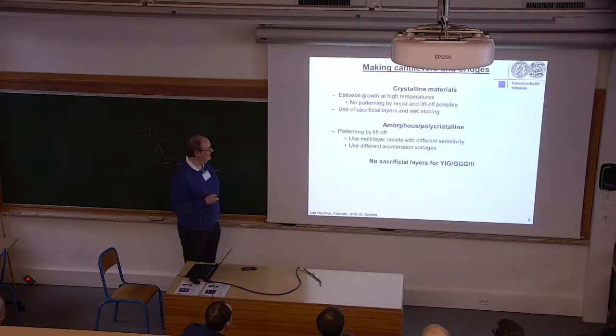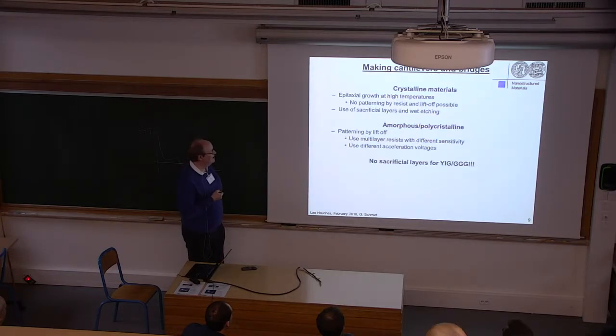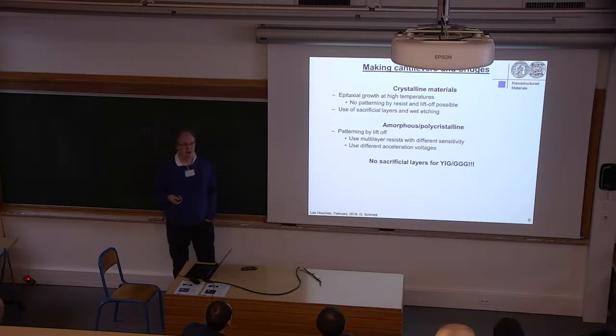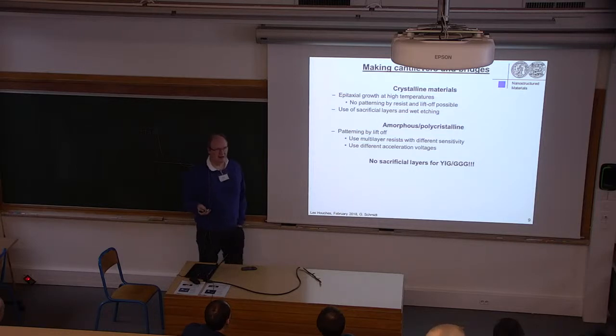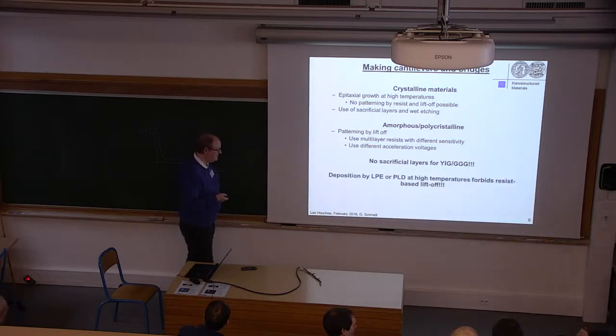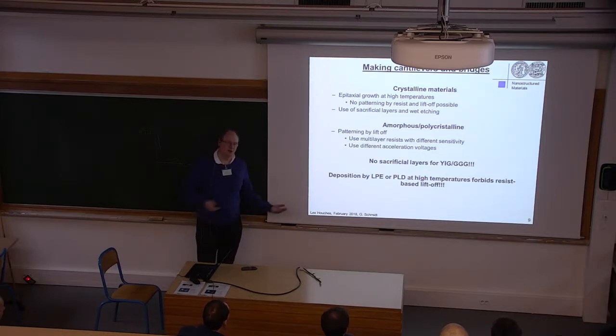So how does this help us? In the end, if you want to use sacrificial layers, it doesn't work, because for YIG you don't have them. The problem is YIG is a garnet, and garnets grow on garnets, or on other garnets, but on nothing else. And garnets are very difficult to etch, especially by wet etching, and there's a high probability that if you can etch the substrate, you will also etch the YIG. So this doesn't work. And also, if you use the standard deposition techniques like liquid phase epitaxy or pulsed laser deposition at high temperature, you cannot use this lift-off process.